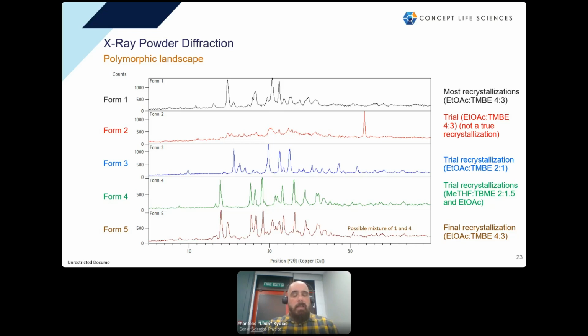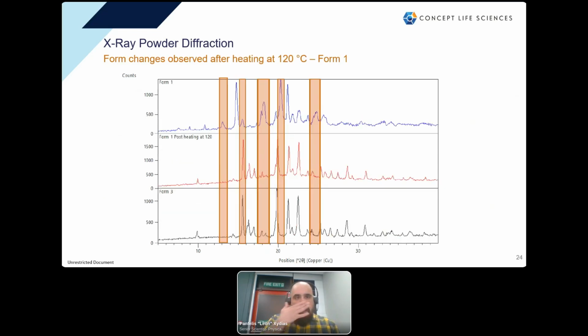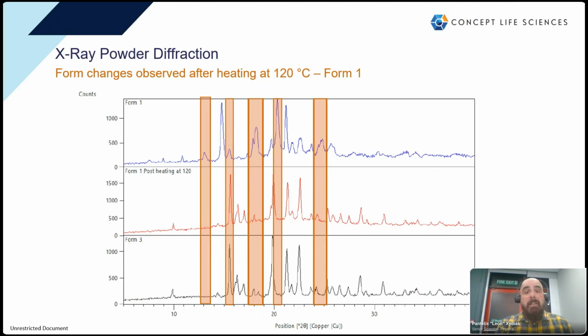This prompted us to see what would happen after we heated it up conventionally at 120 degrees. And interestingly, Form 1, which we had up until that point been considering our basic phase, actually converted to Form 3. Here you can see the diffractograms from Form 1. The red is the signal after it was heated at 120, and in black is the reference diffractogram from Form 3. I am presenting some of the most characteristic peaks, but they're not the only ones. We can see the differences at the higher angles, at approximately 30 degrees, also.